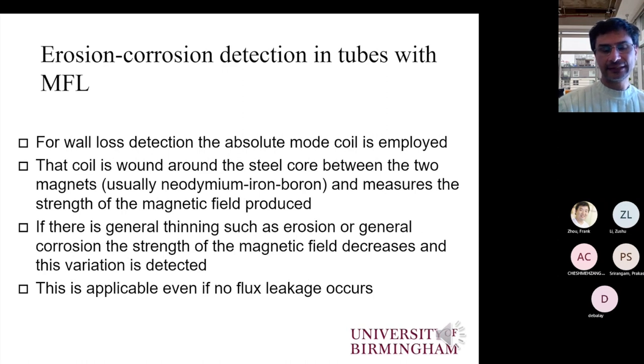So as I said earlier, in MFL, we have two types of coils. The absolute mode coil is employed for general wall loss, instead of the differential coils. The differential coils are the ones that are used for the smaller defects, for the pitting corrosion and potentially for cracks. The magnets are typically based on rare earth, so neodymium, iron, boron, or samarium cobalt are the types of magnets that are typically used.